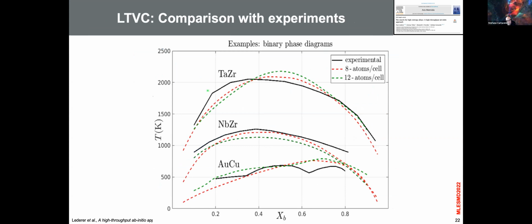Look at here. This is tantalum zirconium experiments, right? This is niobium zirconium experiments. This is copper gold experiments. The black lines are experiments. The green ones, red ones are 8 atoms per cell or 12 atoms per cell. Yes, for every 12 atoms per cell, I need to calculate 50, 100. But let me tell you, 50, 100 order cells are much cheaper than a gigantic tantalum zirconium experiment, which might take years to get all the miscibility gap. And look how it works. It's pretty much the approximation. It's very good, and it works very well.